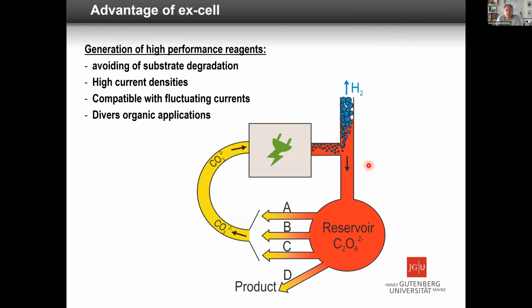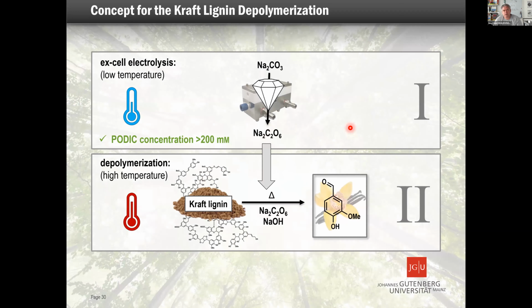And there's one oxidizer I want to show you. This is peroxide dicarbonate. And it's something you can work with in a way that you have a kind of buffer with a reservoir that you can even buffer fluctuating currents as well, and you can separate off the hydrogen very easily. If you use the so-called PODIC, the peroxide dicarbonate, then you do the oxidation at lower temperature and the depolymerization at higher temperature, and this pays off.